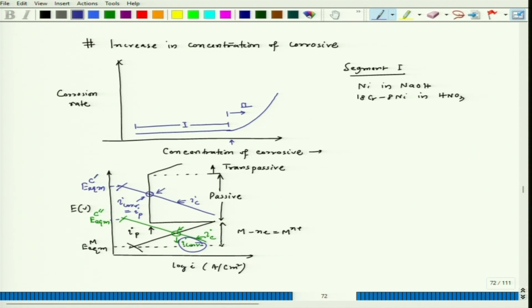So, we want this to happen in the case of an active-passive material, because once we achieve passivity, it can maintain a very low corrosion rate. At the same time, if that material shows a wide range of passivity in a particular electrolyte where it is going to be used, then definitely that passivity will be maintained for a long time, as well as over a wide range of concentration.